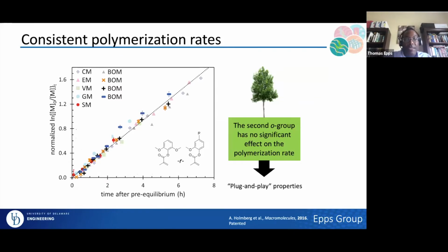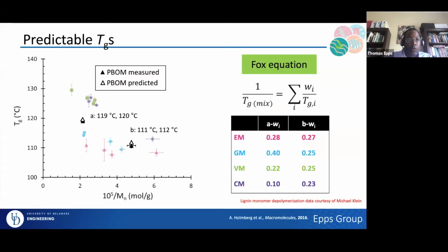So one of the nice things is that we can actually look at polymerization rates for these materials. So I'm putting this here. And part of the reason that I want to show this is because we can polymerize essentially homopolymers, or we can take bio-oil methacrylates, which is basically mixing all of those homopolymers together and doing a polymerization and essentially monitoring the kinetics. But the key point here is that no matter whether I have a single methoxy or two methoxys, the polymerization rate is approximately the same. So what that means is that now we can actually think about using things like the Fox equation and Flory-Fox equation, for example, to predict the properties of our materials as we have basically a statistical or random polymerization in a single block.